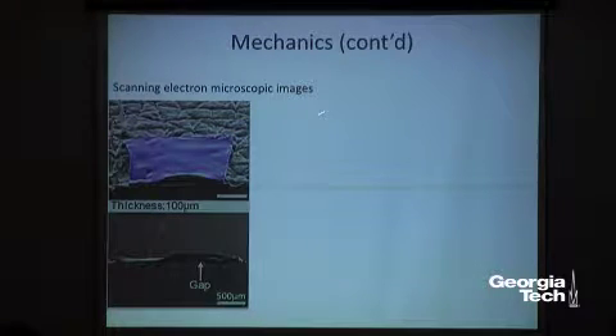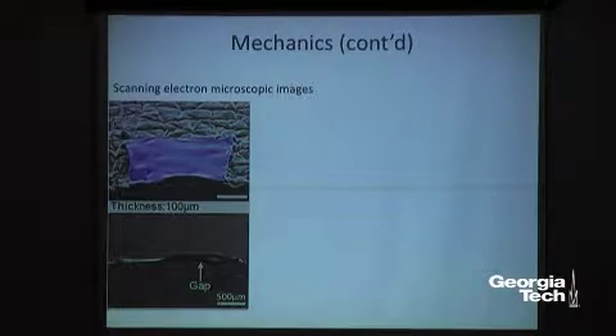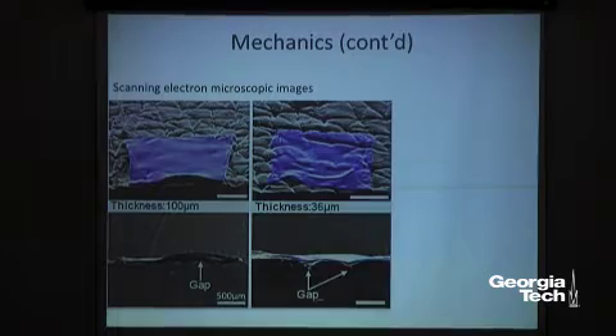So that's a scanning electron microscope image, and here this black background is my skin, right? As I told you, that skin is not flat, right? It has these nice wavy patterns, okay? And I put this electrode membrane having a thickness of 100 micrometers. And now, as you can see, there is an air gap, right? So we have to reduce the thickness further.